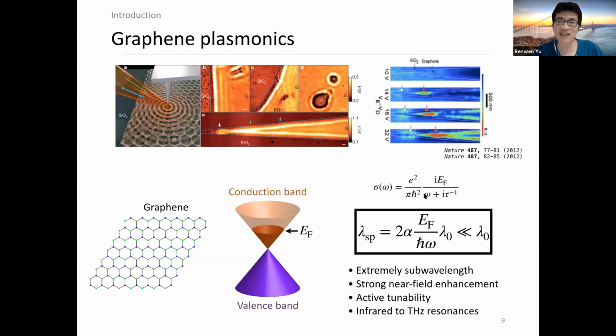In fact, graphene plasmons have been observed already 8 years ago, and the plasmon wavelength of graphene can be expressed in this expression, where alpha is the fine structure constant. Inserting some typical values, we can see that the plasmon wavelength of graphene can be 60 to 70 times smaller than the free space wavelength, so it's extremely subwavelength. It can provide strong near-field confinement, even stronger than noble metals. And if one can tune the doping level by electrical gating, one can tune the plasmon wavelength, as also observed in the experiments. So graphene is really an actively tunable material for many optical devices. And different from noble metal-based plasmonic systems, graphene plasmons are in the infrared to terahertz range, so at much lower energy or much longer wavelengths.